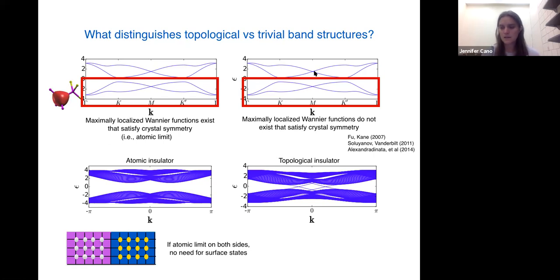If you put this next to some normal insulator, then somewhere there needs to be an inversion. You need to have all S or all P. And so the conduction and valence bands need to unswap or uninvert. And that band closing is exactly the way that you get gapless surface states. So this is our operational definition of a topological insulator: one which does not have maximally localized Wannier functions that satisfy crystal symmetry. We'll define the converse of that, the trivial insulators, as these atomic limits, which do have maximally localized Wannier functions.